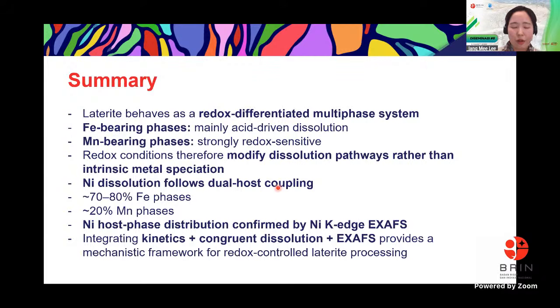from the congruent dissolution, and then we found from 70 to 80% is from the iron phase, and 20% of the nickel is from the manganese phase, and then nickel host phase distribution. This distribution was also confirmed by the nickel K-edge XAFS signal through the fitting with the two different crystal structures. And through this study, I would like to integrate kinetics and congruent dissolution and XAFS, and it may provide some insight in terms of the mechanistic framework for the redox controlled laterite processing.